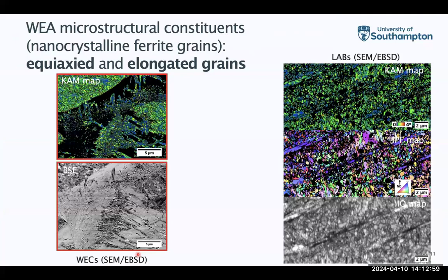Also, in terms of the microstructural constituents in those different features, we found that there are 2 main constituents, which we call equiaxed and elongated grains. They are all nanograins. As you can see from the EBSD map, these are rounded grains. This is an SEM BSE image. You can see these are the equiaxed grains, and these are elongated grains, so they are longer. They're not just globular grains.